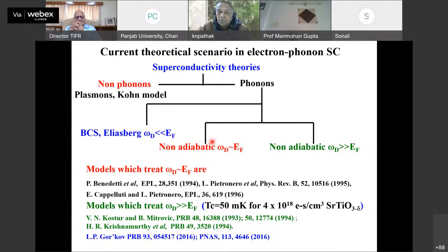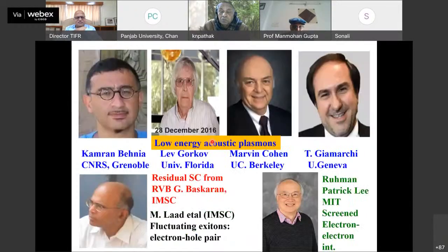So the adiabatic ones, we know that it is going to be non-adiabatic because the thermal energy and the electronic energy are comparable. Lattice energy and electronic energy are comparable. So there are several models which predict for this. The best lowest carrier concentration superconductor before our discovery of bismuth is strontium titanate, which is an order of magnitude higher than ours. And there are several models which try to tell you that it is completely not the BCS, it is some other mechanism. The mechanism is still not settled even in strontium titanate.